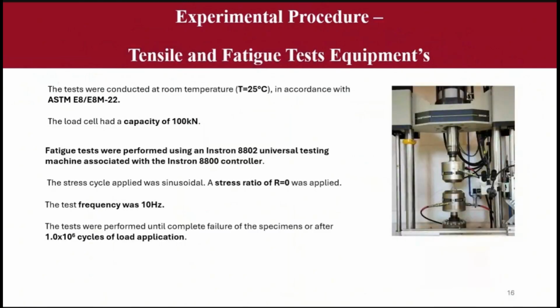Here we can see the tensile and fatigue test equipment. We use a universal testing machine with a capacity of 100 kilonewtons. The temperature was room temperature. For the fatigue test, we use a stress ratio of 0 and a frequency of 10. The tests were performed until complete failure of the specimens or after 1 million cycles of load application.